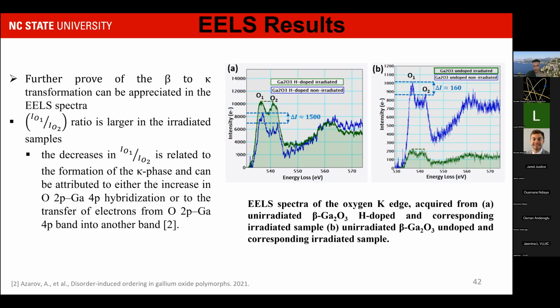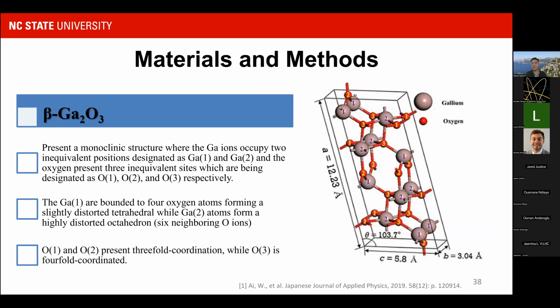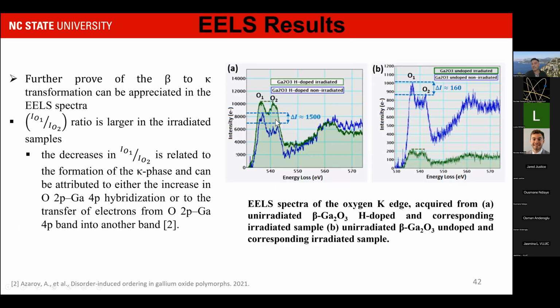There was further proof of this beta to kappa transformation that can be assessed by looking at EELS spectra, and looking especially at the ratio between the O1 and O2. O1 and O2 are the oxygen based on their position here. They are not equivalent. So when we look at the ratio of those intensities, first we see that they clearly change after irradiation. And the decrease in this intensity ratio is related to the formation of the kappa phase.